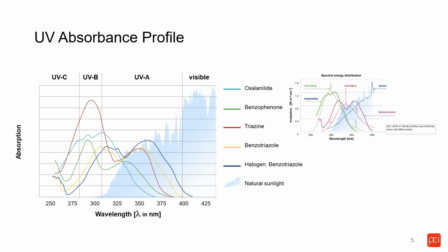Another important feature of the UV absorber, in addition to the photopermanence, which again is a critical factor in order to select the UV absorber that will give you the best durability for your application, is the absorbance profile of those UV absorbers. As you can see in this graph, a benzotriazole, a triazine, or oxanilide don't really absorb in the same wavelength. And when we compare those absorptions to the natural sunlight, which is the graph in the back, the natural sunlight intensity actually increases as you go from short wavelength, the UVB area, to the visible light, which means that with the intensity increasing, you will have more photons, for instance, at 375 nanometers than you have at 300 nanometers.